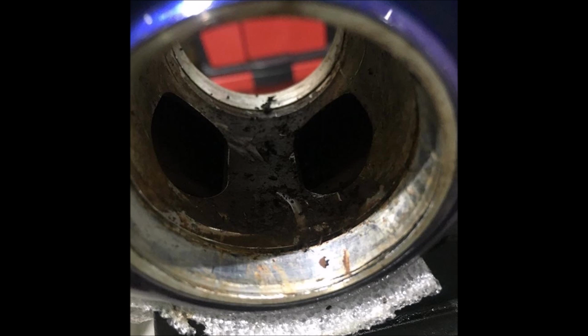So that water just sits in there, and eventually the water becomes so high it comes up through those holes and starts to attack the steel bearings from the inside. And this dirt and rust that you can see in this picture is a result of that damage to those steel bearings. Unfortunately, I'd already knocked out the steel bearings at this point, but I can tell you now they were very, very badly rusted.